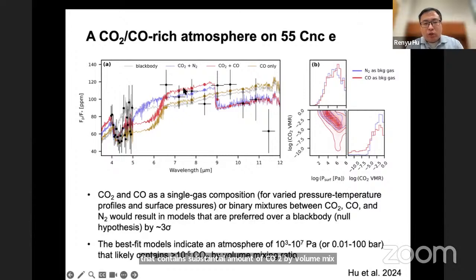In this correlation plot, the correlation between the volume mixing ratio of CO2 and the surface pressure indicates that the spectral modulation here in 4 to 5 micron constrains the column density of CO2 in these models. Also, the posterior of the CO2 has a tail towards a small mixing ratio if carbon monoxide, CO, is assumed as the background gas, which indicates that a CO-only scenario is also possible.